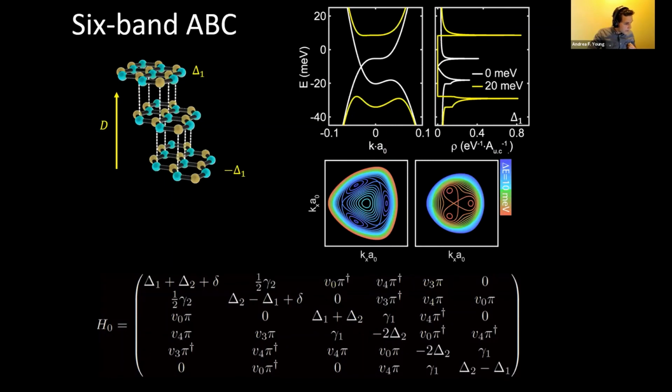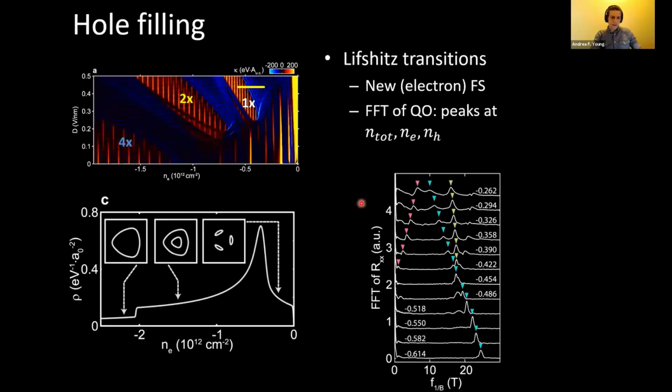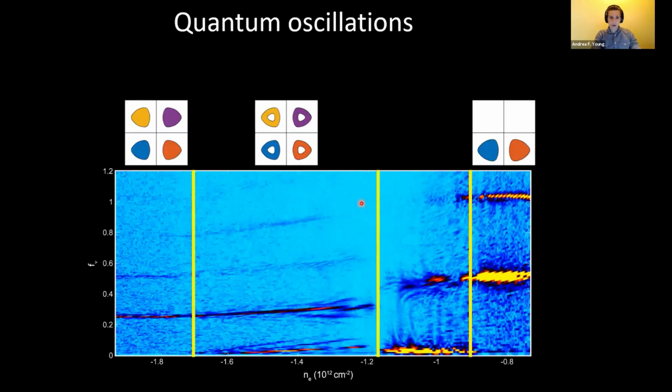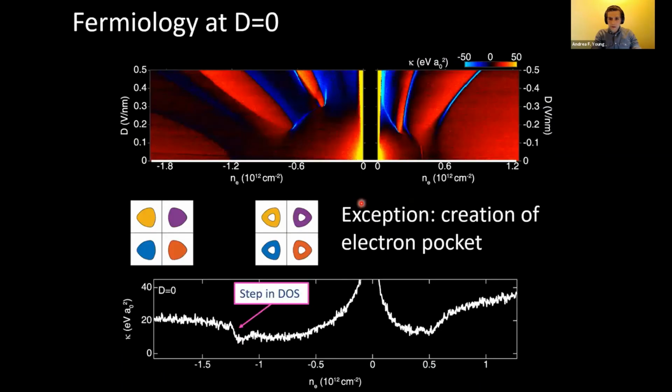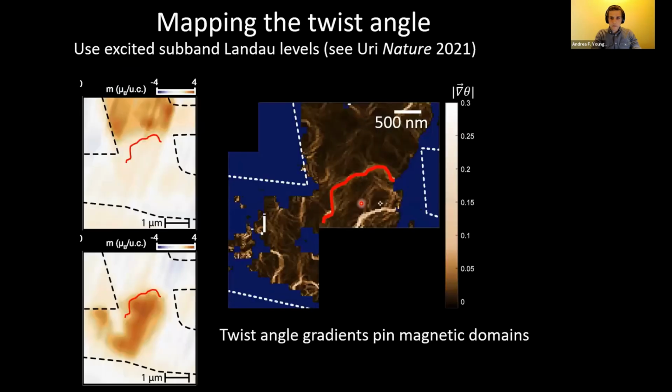What's the broadening of the twist angle inhomogeneity? Is it possible to realize superconductivity in BLG or TLG? The broadening of the twist angle inhomogeneity, I'm not sure exactly what units you want there, but it's similar to what was observed by STM groups and by Ellie's group. It's kind of comparable. I can look at the numbers, but 0.01 degrees over some tens of microns. This is, I think, in degrees per micron or something like that.